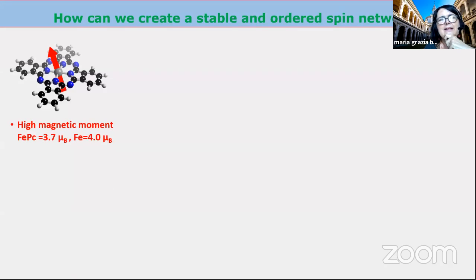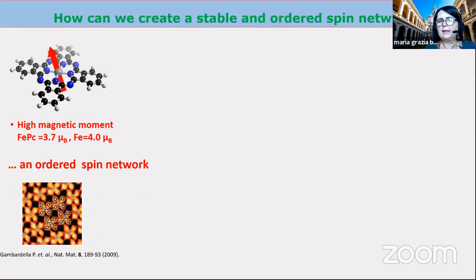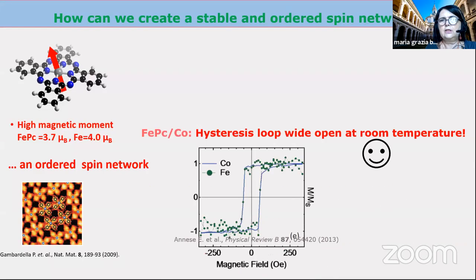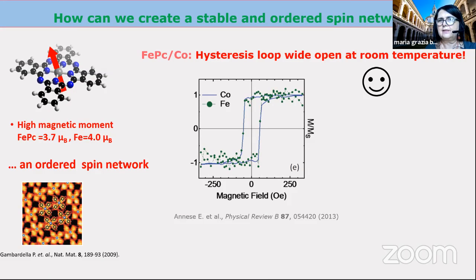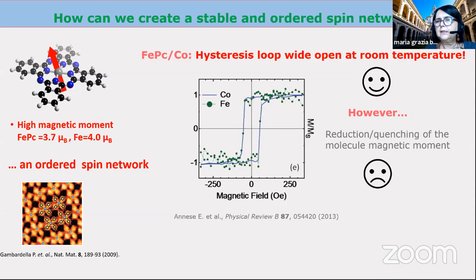So there was another study, and in this study they used iron phthalocyanine. Iron phthalocyanine is interesting because it has a very high magnetic moment comparable to a single iron atom. And it's easy to make an ordered spin network with this phthalocyanine because the molecule-molecule interaction allows this very nice ordered configuration. So also in this case, they tried to measure the hysteresis at room temperature, with a magnetization that is non-negligible, but there was a big reduction, almost a quenching of the magnetic state. So it was very difficult to measure for this reason. There was a big reduction in the magnetic moment of the molecule.